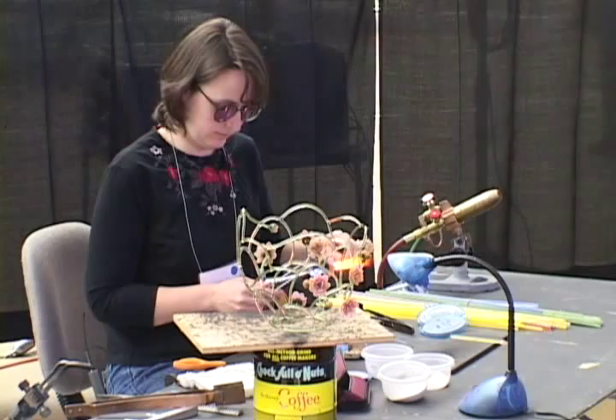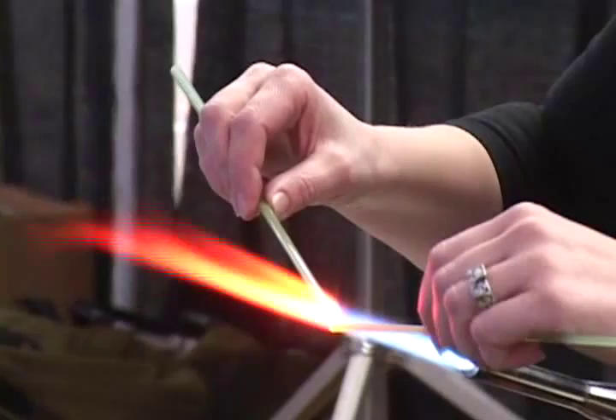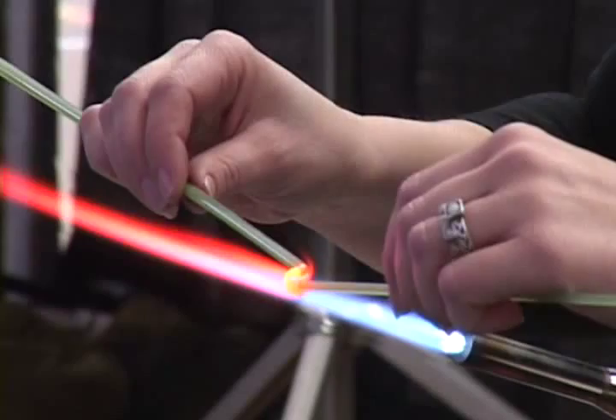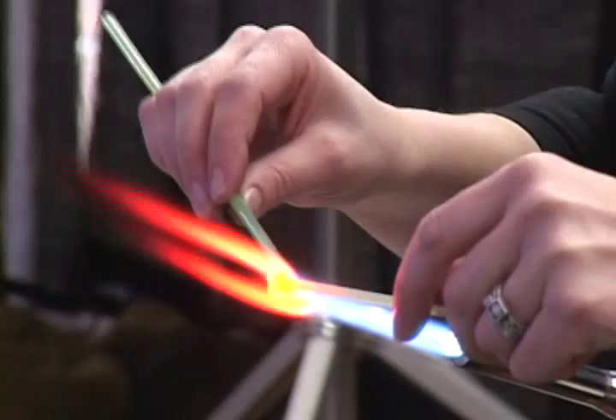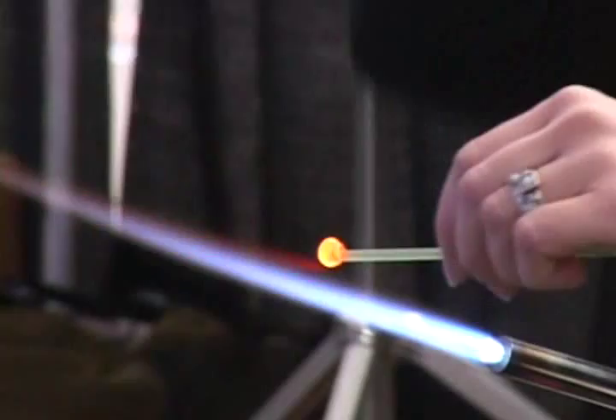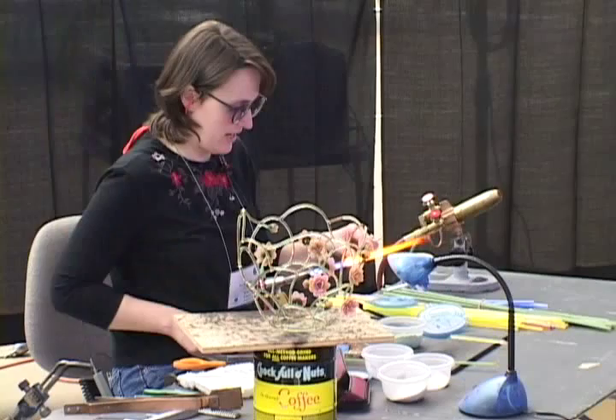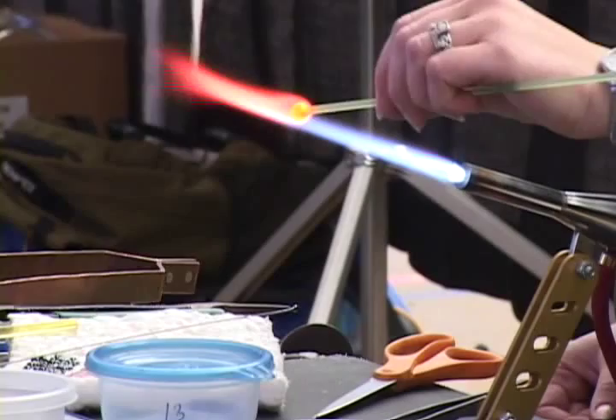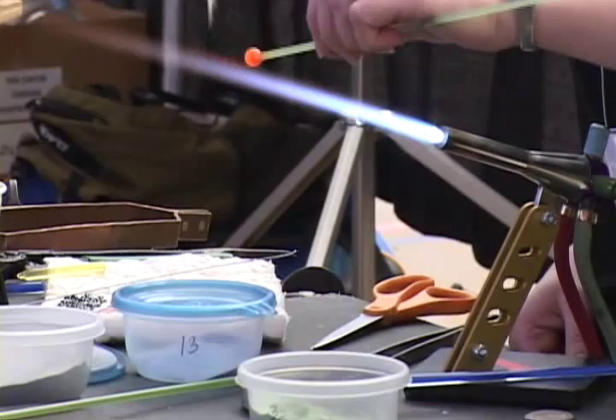There's so much that we have to do that I can't imagine melting my own colors and then fritting and powdering them. I tried a little bit of ball milling. At school, we'd be able to melt tanks of colors, and I tried making my own powder and frit, but you have to be really careful. We had a ceramic ball mill, and you'd put a certain amount of the ceramic material into the glass as it was ground, and then we'd experience color and fitting problems with that. Our friend Rob Levin suffered a lot of health problems from melting his own colors, and that's just something I've never felt the need to do, and we're really fortunate now to have such a variety available.